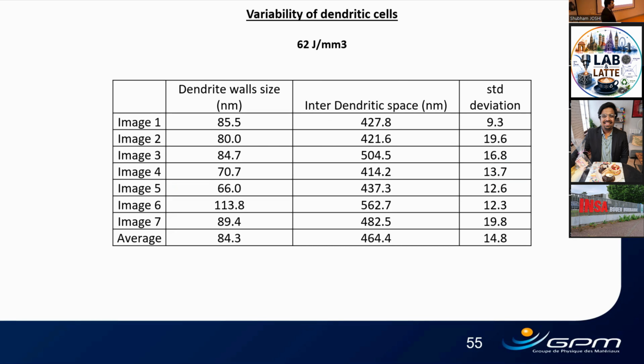And there is also a correlation between the cell size and the wall size. I mean, the thinner the cells are, the thicker are the walls, or not. Well, you only did this for this energy density. Yes, the wall size has been done for only one energy density, but the average interdendritic cell size has been done for different densities as well. But I don't know if it's correlation or causation. It seems so here, but we are not sure. Okay. But certainly, I feel if the walls are thicker, that means the dislocations might need more stress to go away. Yeah, so certainly physically there should be more there. But it's a prospect again.